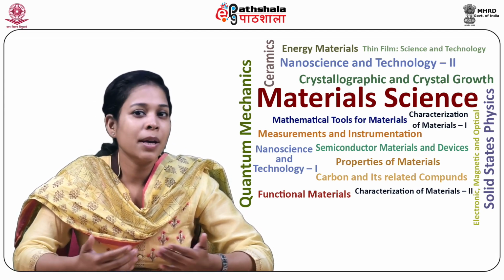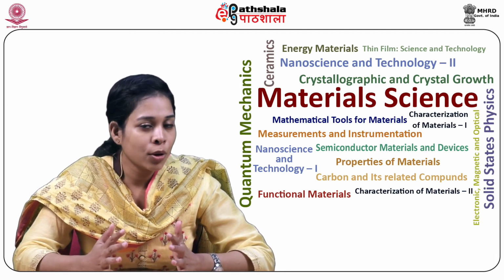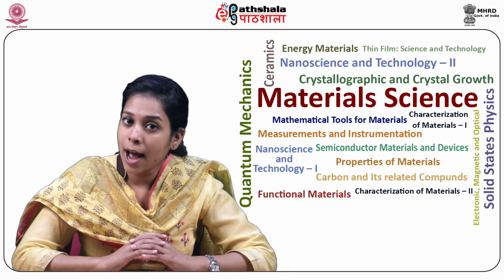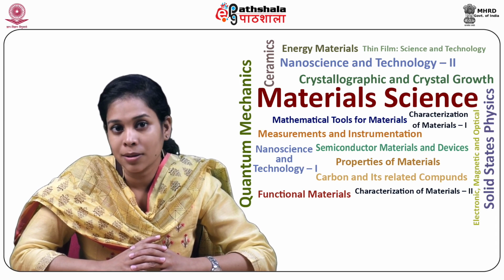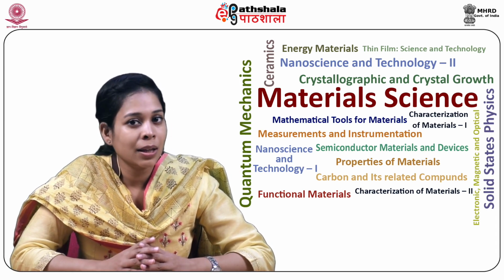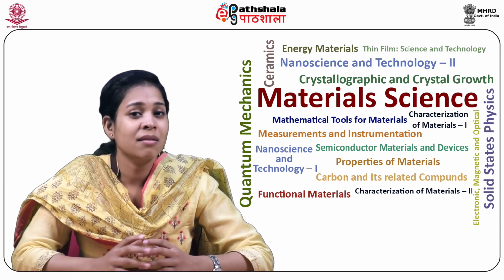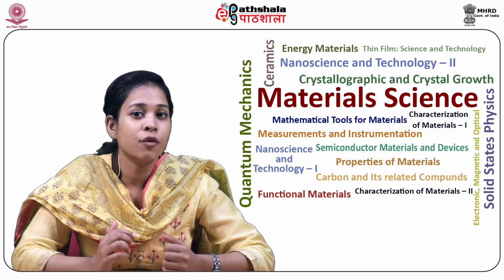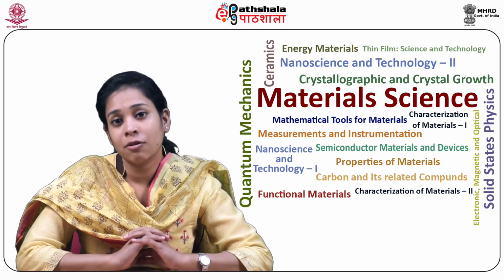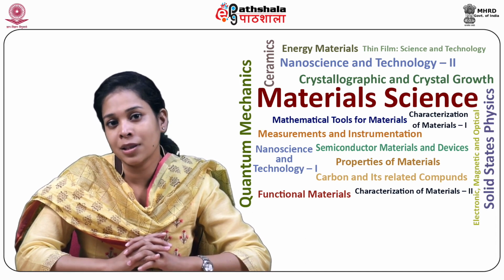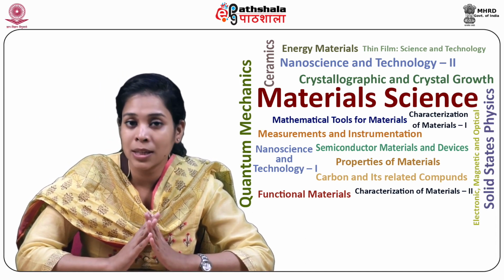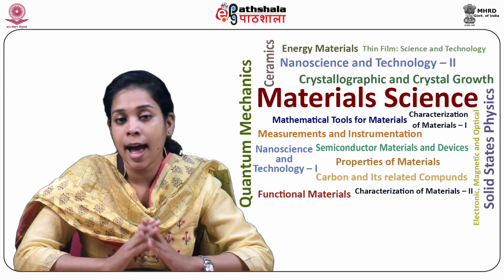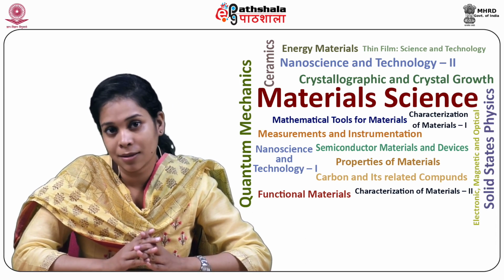Most ceramic materials are neither purely covalently nor ionically bonded. In most ionically bonded materials, there is a significant level of covalency, which decreases as the difference between the electronegativities of cation and anion increases.